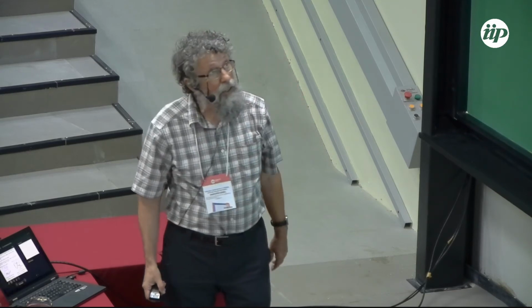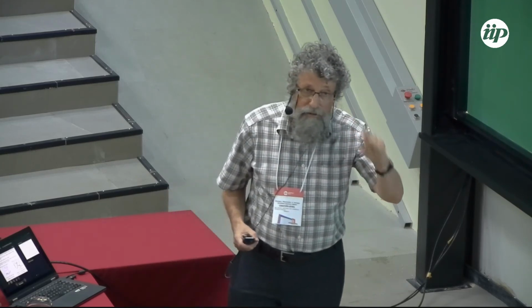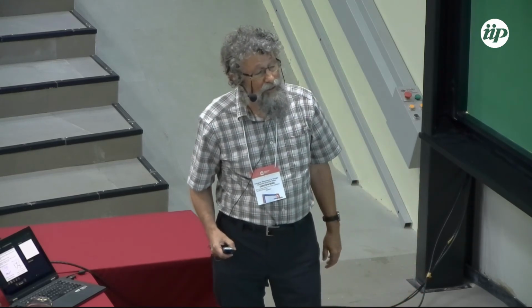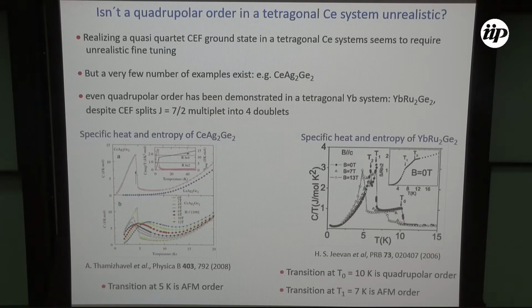So the question one might have is: isn't a quadrupolar order in a tetragonal system, where one expects completely separated doublets, something very unrealistic? Because it seems to require a very strong, unrealistic fine-tuning to get two levels so close that you have effectively a quartet. But that is not true, because there are already a few examples where a quasi-quartet is realized in a tetragonal system. One cerium system is, for example, CeAg2Ge2. Here I show the specific heat, taken from this paper. It's not our own work.